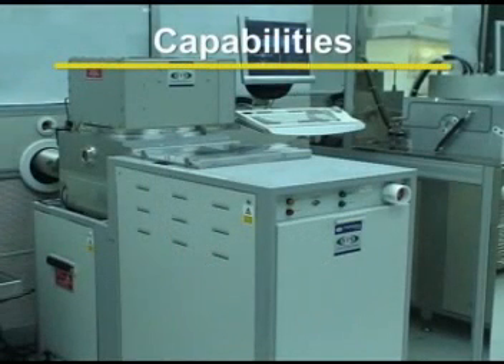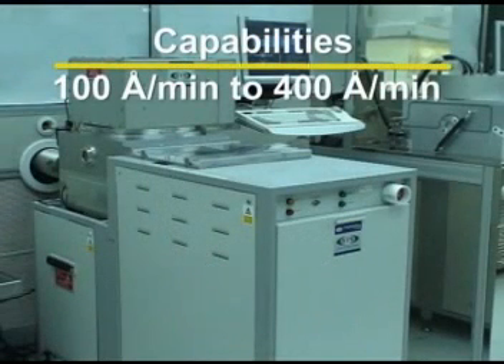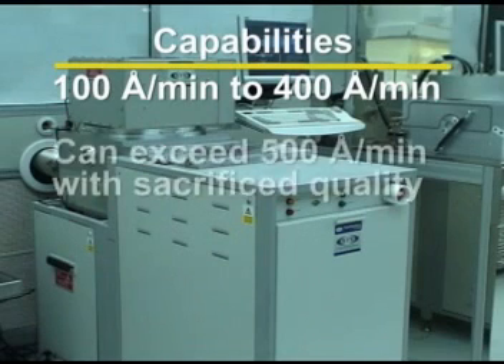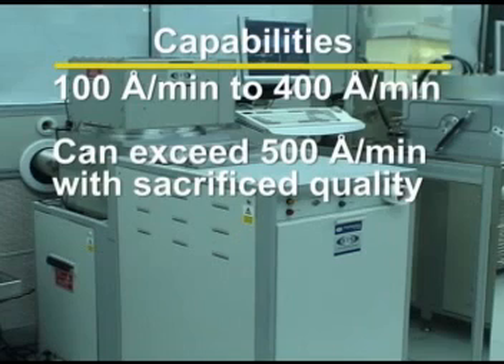Typical deposition rates on the STS system range from 100 angstroms per minute to 400 angstroms per minute, depending on the levels of power, pressure, and gas flow. It has the capability to deposit silicon dioxide at rates exceeding 500 angstroms per minute. However, the quality of the deposition may be sacrificed with the increased rate. This simply allows for a thick sacrificial layer of silicon dioxide to be deposited more quickly.